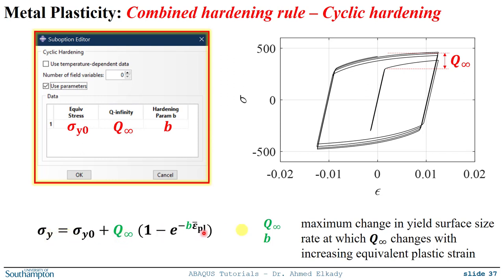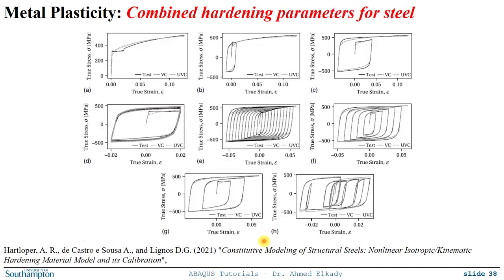Now, we mentioned that the Q infinity and B parameters, as well as the C and gamma that we discussed previously, are not unique, so you can get different combinations of them to get the same behavior. So the appropriate way is to do a calibration of your material model with different coupon tests that involve different loading histories. So you have your typical uniaxial monotonic test, you have the symmetric cyclic with constant amplitude, you have one with asymmetric cyclic strains, and with ramped cyclic strains. So you need to do a number of histories and then fit or calibrate your model against those in order to obtain the best parameters that fit the data.